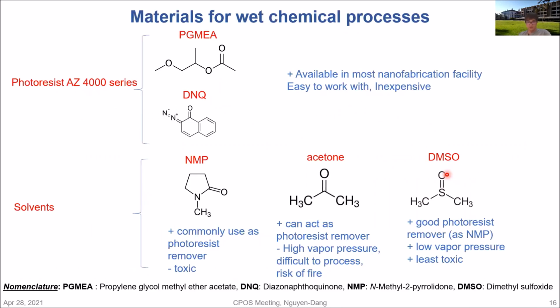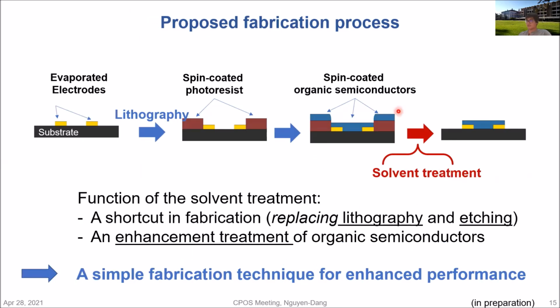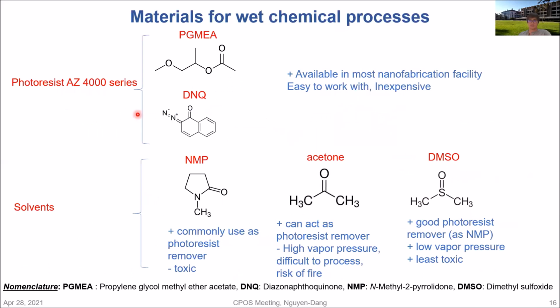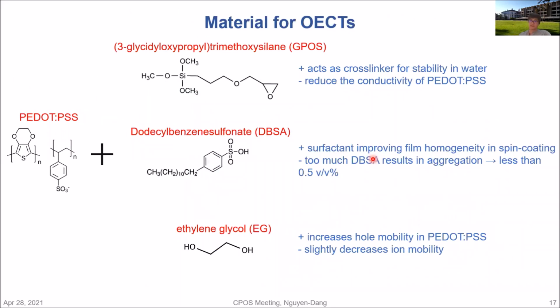In order to demonstrate these techniques, I selected several relevant materials. First of all, for the photoresist, I chose the very common AZ4000 series. That is one of the most common photoresists available in all clean rooms. It's very easy to work with, and it's very inexpensive. This material can be dissolved with polar solvents like NMP, acetone, or DMSO. For the OECT, I chose the most widely used material, PEDOT:PSS, because if it works with PEDOT:PSS, it can have a bigger impact.